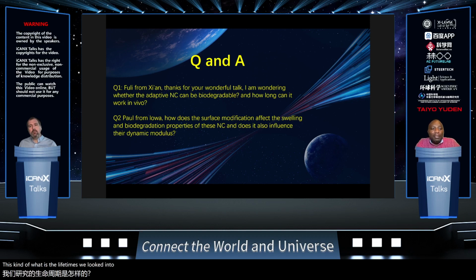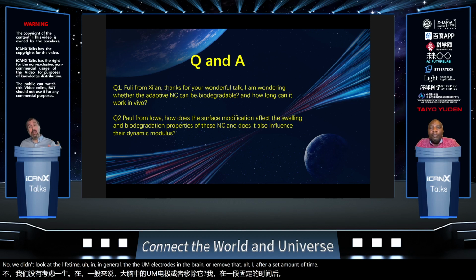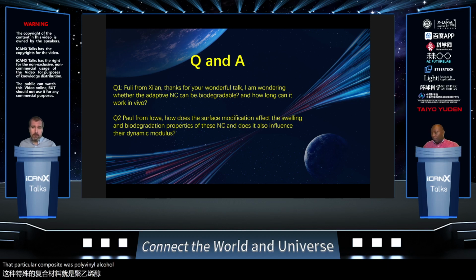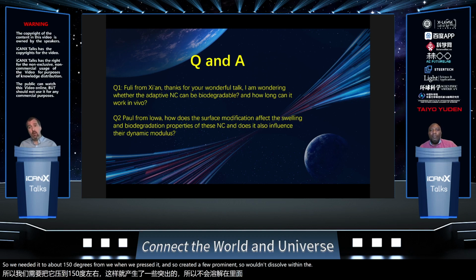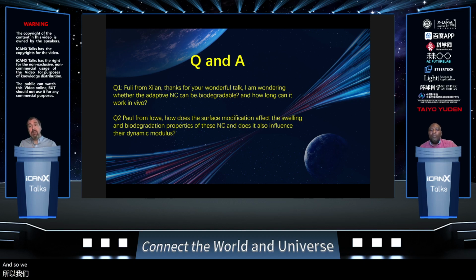We looked into that. No, we didn't look at the lifetime. In general, the electrodes in the brain are removed after a set amount of time. That particular composite was polyvinyl alcohol. Our polyvinyl alcohol in that case was slightly cross-linked, so we heated it to about 150 degrees when we pressed it, and so created a few cross-links so it wouldn't dissolve within the body. You didn't want the polymer to roam around the brain. So we very specifically made that non-biodegradable within the body. You generally do not want polymers to degrade inside the brain, as a general statement.